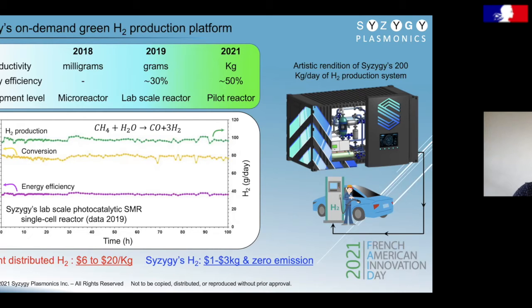Here is the data from our 2019 test. Using steam methane reforming as an example, you can see stable hydrogen production over the course of 100 hours of test. And the amount of hydrogen is 100 grams per day from our lab scale reactor, at an energy efficiency of above 30%, and conversion of the products of about 70% in a single pass. And here you can see our artistic rendition of our future field trial system, which is capable of producing 200 kg of hydrogen per day, which is about the full tank of about 40 hydrogen-powered vehicles. So we are planning to make a hydrogen fuel station based on this system.